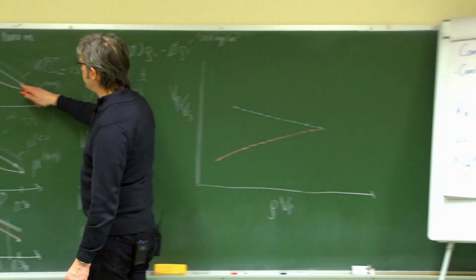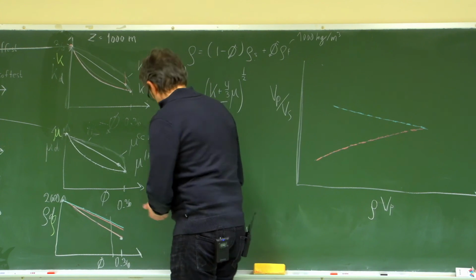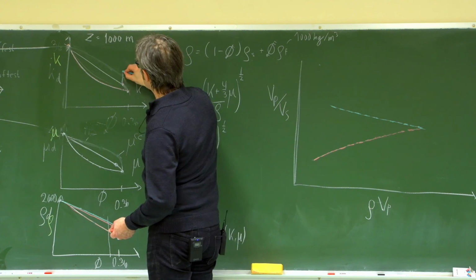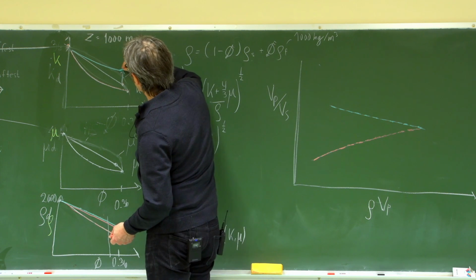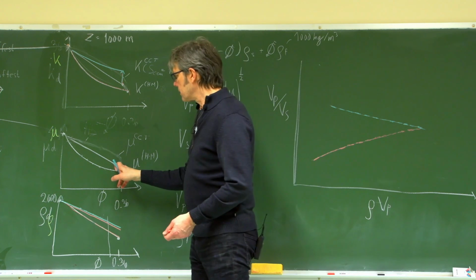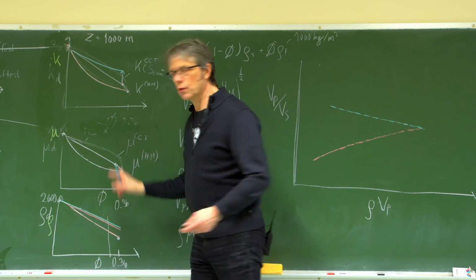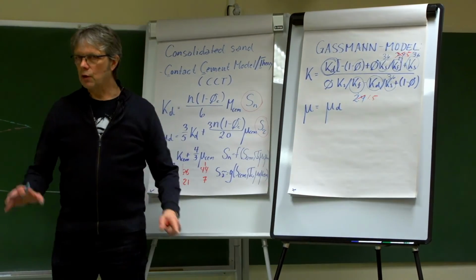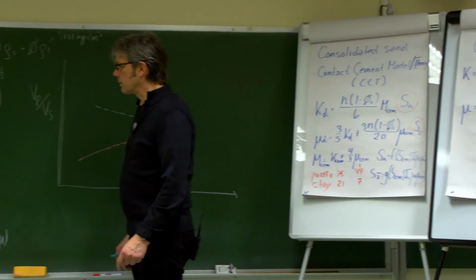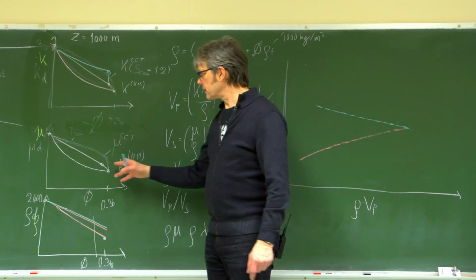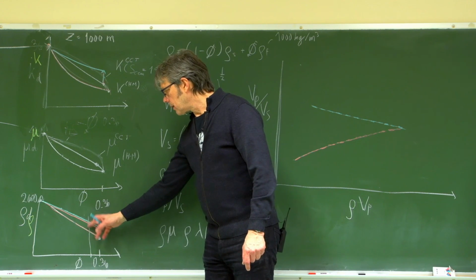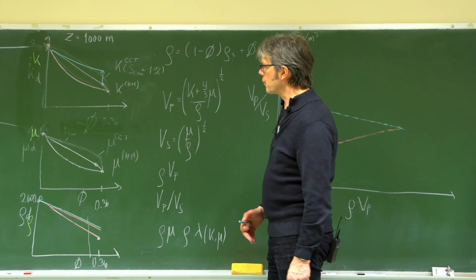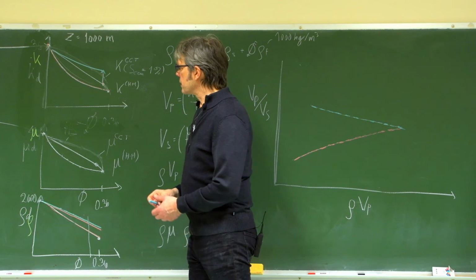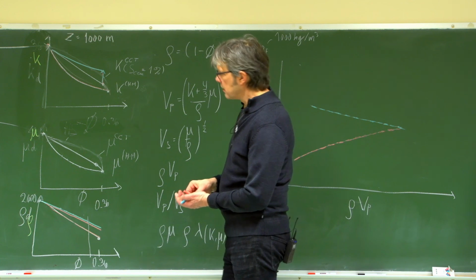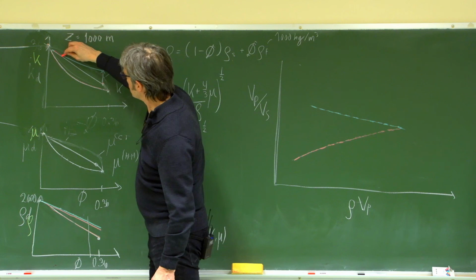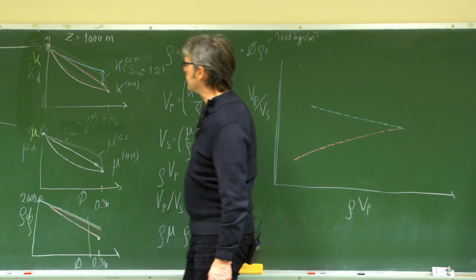So again, I start filling my endpoint here. Let's use the blue to be consistent here with water. So I have a water saturated line here. No effect on the shear modulus according to Gassmann here. It says that, well, as long as you know the dry rock properties, water does not play any role into that. And then we have the fluid that just follows the same trends or lines as before. So I can do the same for the gas, and it would, of course, hardly move up from this dry rock line.